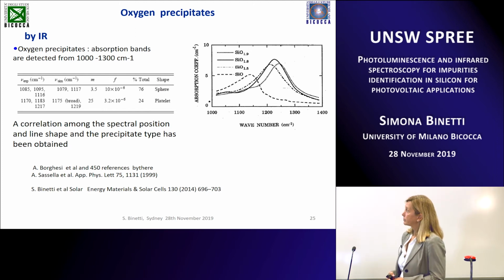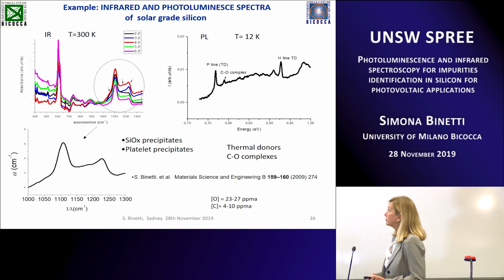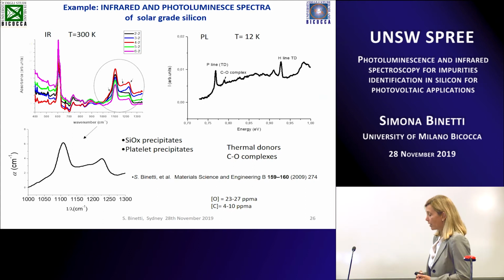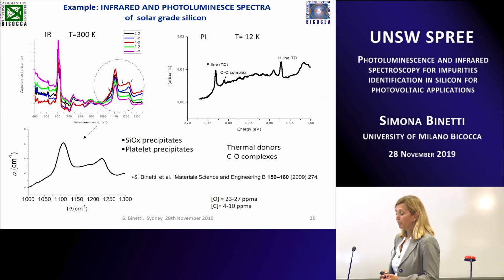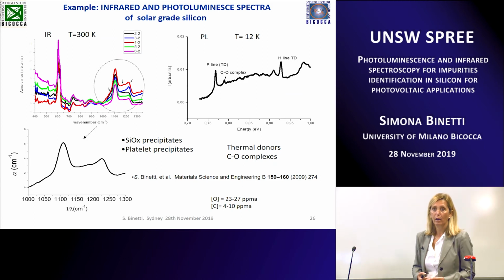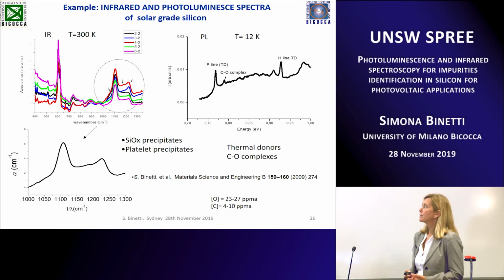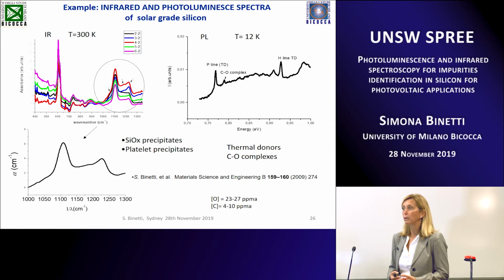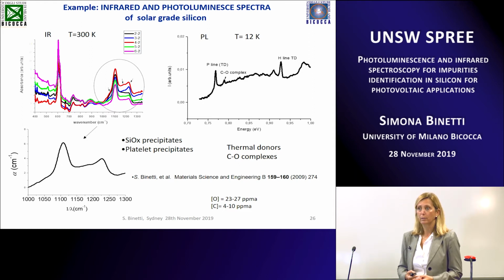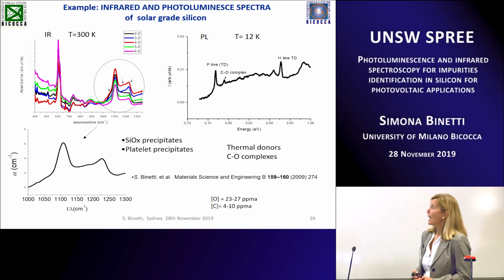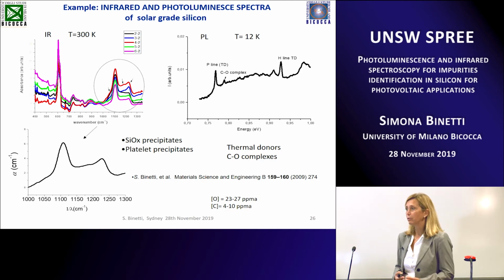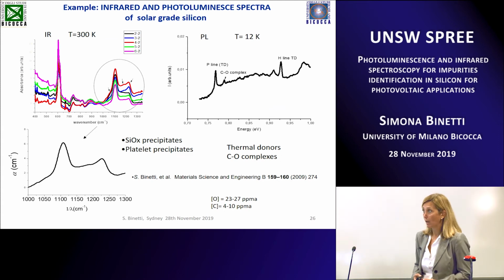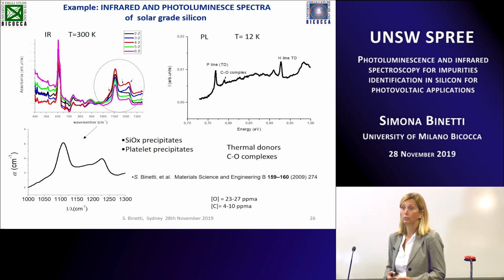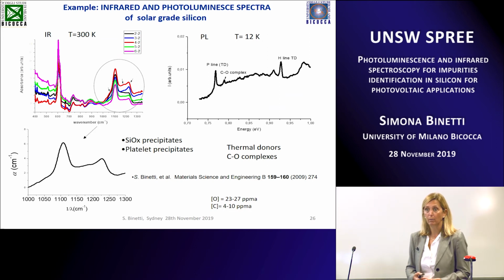And this can be very useful. For instance, many years ago we were studying, in the frame of a European project, the possibility of using metallurgical grade silicon for PV application. We have seen that in some of these samples there was such a high concentration of oxygen that we saw at room temperature the oxygen precipitates, and the band here indicated in the circle. And in the same sample, by photoluminescence, we have seen a lot of defects. We have seen all the bands related to carbon and oxygen, the P line, and we have also identified, by the shape of the oxygen precipitates band, the type of precipitates that we have. And then we made a correlation also with transmission electron microscopy, which is a much more time-consuming measurement to be performed.